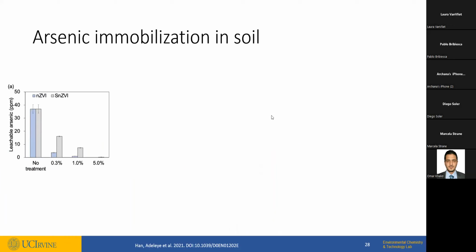So here is a test we did on the nanoparticles just in soil with no plants. And this is to check the first box. Can these nanoparticles immobilize arsenic? That was our primary target for this study. Can it immobilize arsenic in soil? So here's what we found so far. If we don't treat the soil, actually, to start with, we introduced 50 parts per million of arsenic to the soil. About 37 parts per million was leachable. Leachable means if water gets into the soil, it can wash off the arsenic. So about 37 ppm could be washed off.